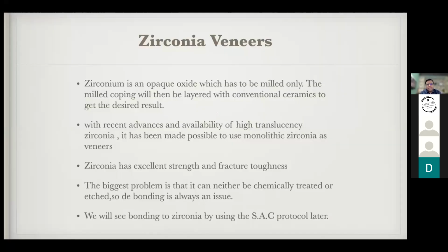Now, there were zirconia veneers that came up in the market, but frankly, they just went away because the biggest problem is that zirconia cannot be chemically treated. So it cannot be treated with hydrofluoric acid. You will not get the etching pattern where the resin would go and bond. So if you do not bond, it will debond. And although you have zirconia bonding by using the SAC protocol,